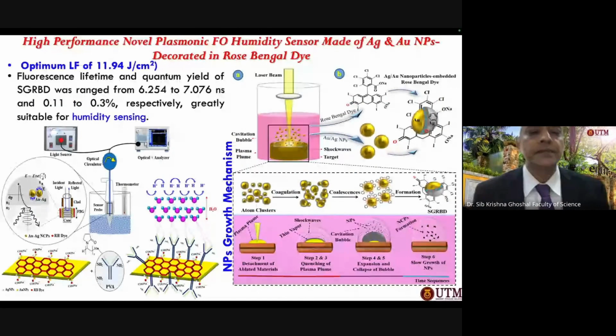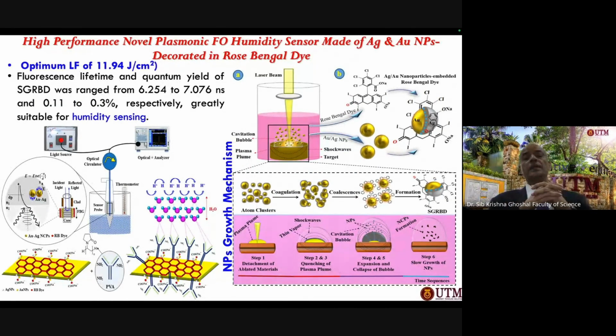So here is basically the kind of nanoparticles that we use in rose Bengal dye. We use different laser fluences, and out of many laser fluences, many samples we prepare. I will be just showing you the optimum fluence at which we got the best nanoparticle, 11.94 joules per centimeter square.